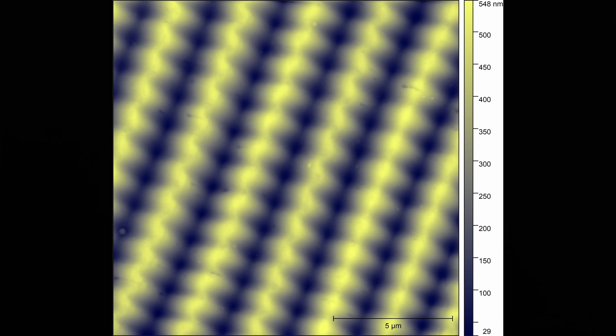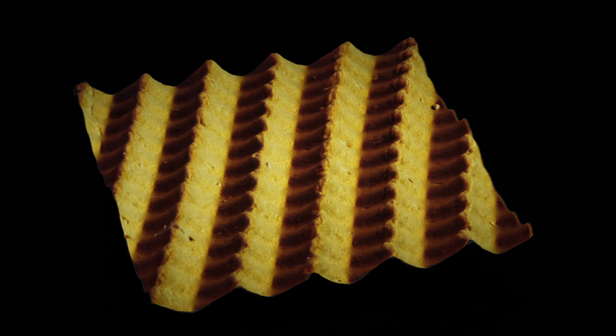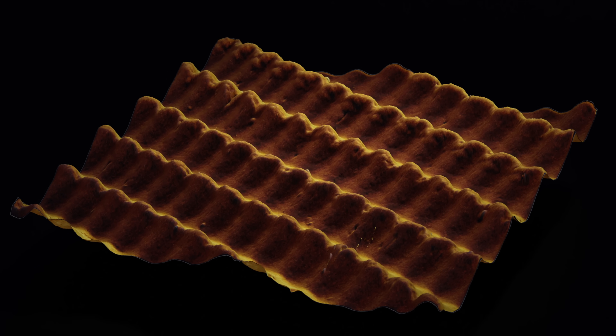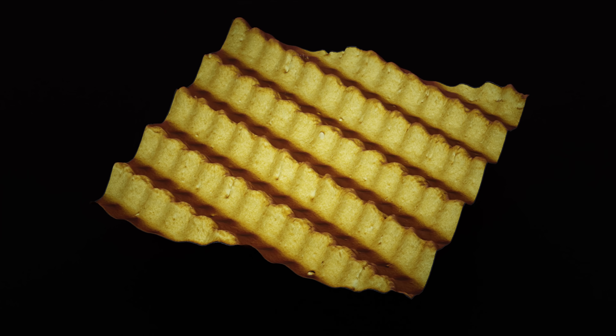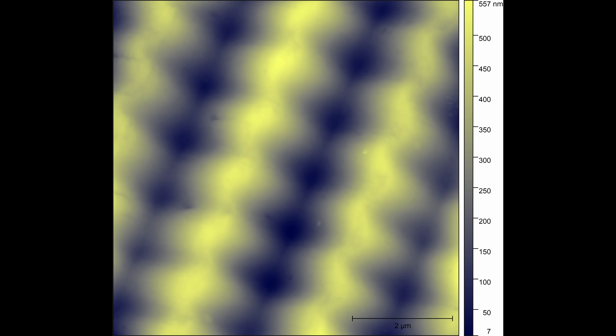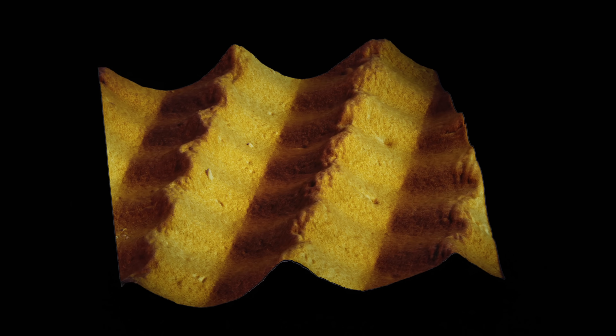The faint ripples and undulations that we saw under the scanning electron are now very apparent. The AFM allows us to reconstruct the surface in a three-dimensional model, which makes the pattern of data encoding much more obvious. The stylus of a CED is designed to be too large to fit inside any individual depression, instead riding smoothly across the average height of the groove. The disc itself is conductive, using a carbon-filled PVC material, and the stylus contains a small electrode at the tip. This means the electrode is separated from the conductive disc by a small height, forming a capacitive circuit. As the stylus runs along the groove, the undulations change the distance from the disc to the electrode, and this in turn changes the capacitance. The stylus is, in effect, measuring the distance to the base of the groove in a continuously variable analog manner.